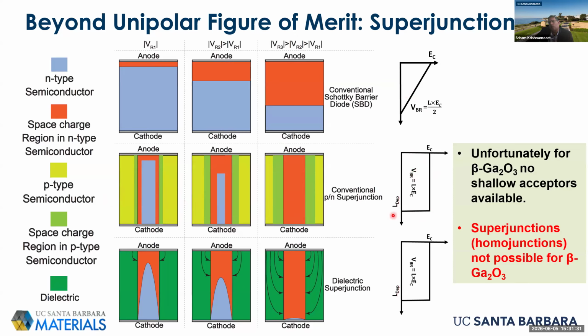So you get twice the breakdown voltage, but more importantly, the fact that you have these alternating pillars of P and N-type region means that you can now dope the material heavily and still deplete it. And so that gives you a much lower on-resistance. So the win in a superjunction is not just twice the voltage, but actually a much reduced on-resistance, because now you're able to dope the material higher and still deplete it using these columns of charge-balanced P-type and N-type materials. So to do something similar in gallium oxide is going to be hard because we don't